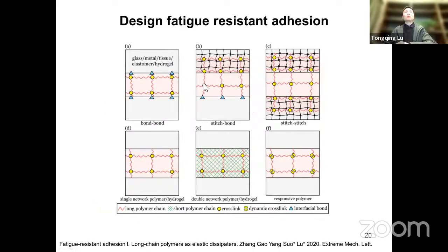And this design, we believe, is applicable to many different kinds of adhesion. For example, this adherent can be glass, metal, tissue, elastomeric hydrogel, any kind of material, as long as it can form some chemical bonds here. And as long as you use this long chain polymer network, the fatigue threshold of the interface will be very high. There are many different combinations of different adherents. Okay.